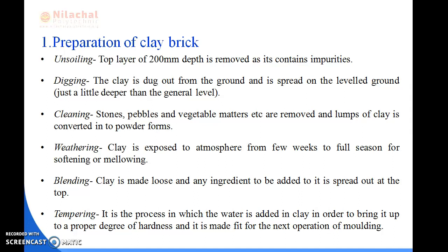Next, weathering. After all the particles have been removed, the clay is exposed to the atmosphere for a few weeks to make the clay soft. After the clay is soft, if any ingredient is to be added, it can be spread on the top. Next process is tempering. After all these processes, water is added to the clay to make a paste, or a proper degree of hardness, to make it fit for the next operation, that is molding.